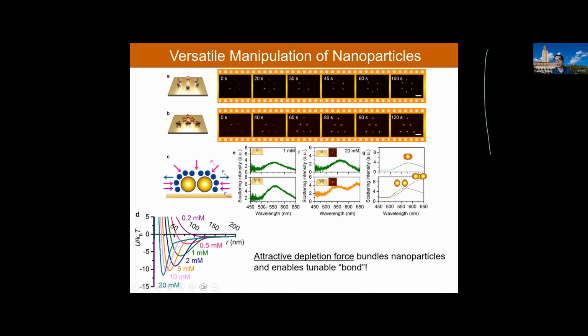We know that in plasmonics, when particles are close enough, near-field coupling can induce a longitudinal mode. For an otherwise spherical particle, there is only one dipole mode. With the longitudinal mode and the transverse mode, you can have two peaks. These two peaks depend on the distance, and the distance depends on the concentration of the micelles.